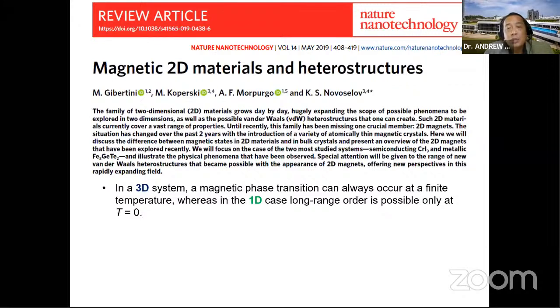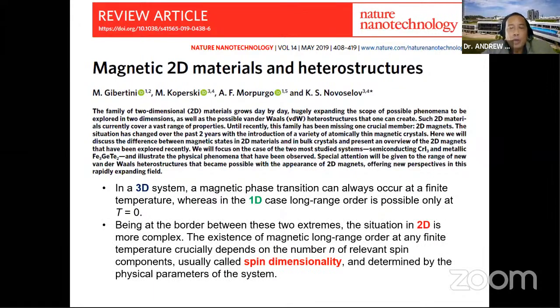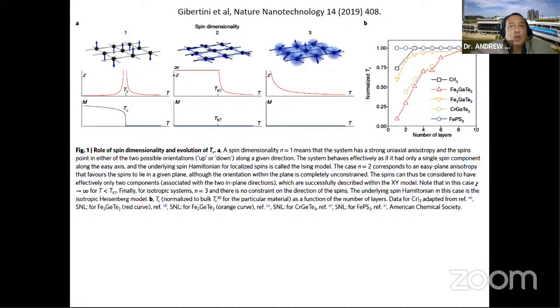So in a 3D system, you always see a magnetic phase transition. You always see a finite Curie temperature. But in the 1D case, the long range order is only possible at T equals 0. So that's the limitation of the dimensionality of the material. Now, 2D is somewhere in between. 2D materials can have a finite Curie temperature, but it depends on the spin dimensionality n, which I'll explain in the next slide. So this explains the spin dimensionality.